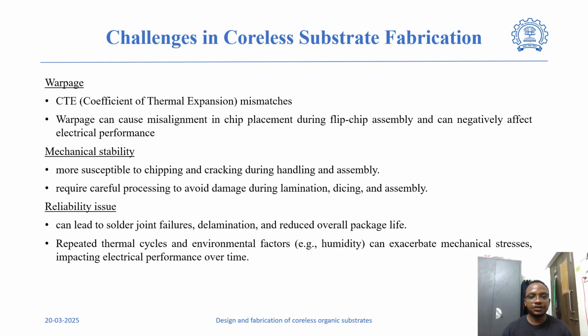There are a few challenges in Coreless substrate fabrication, and the most significant challenge is warpage, and this is due to the fact that without a central core, the build-up layers are thinner and more prone to bending. Coefficient of thermal expansion mismatches between copper, dielectric layer and adhesive induces residual stress during curing, and this causes misalignment in chip placement during flip chip assembly and can negatively affect electrical performance.